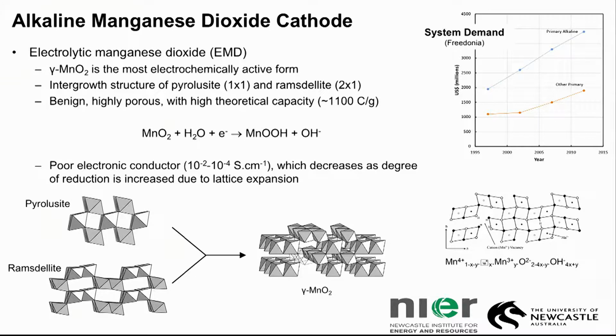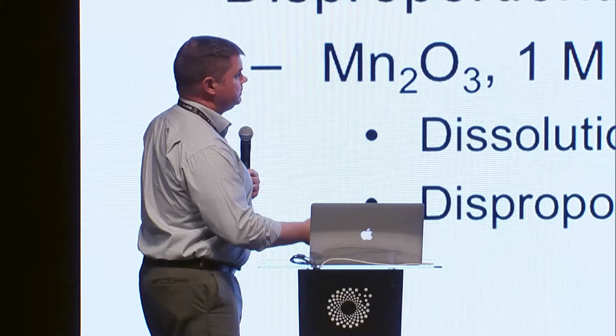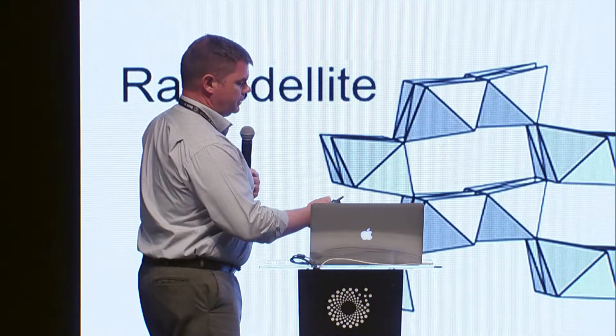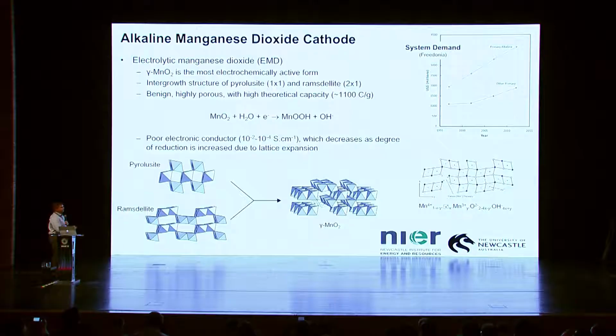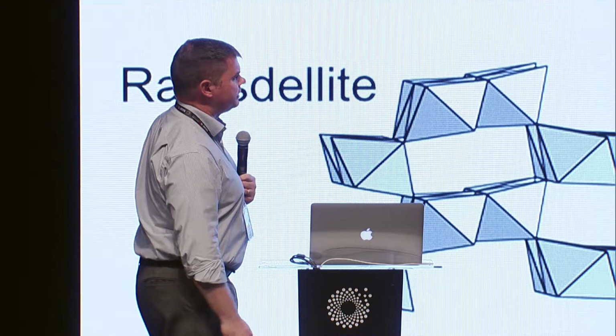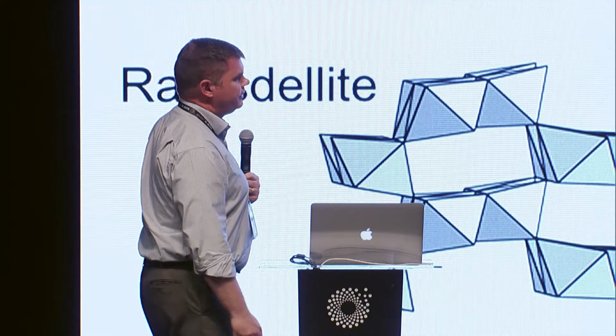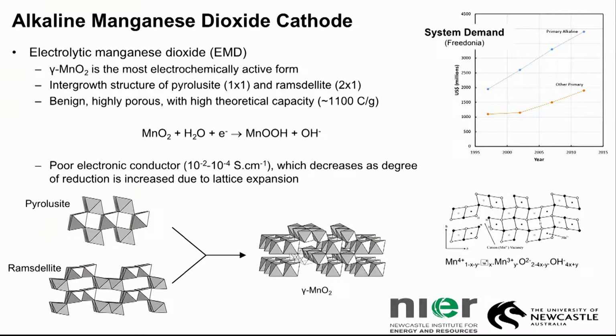But still, it's a very, very high volume system. And you can see here, keep pressing the wrong button. So you can see here in the top right-hand side basically how the dollar value of the primary alkaline system is continuing to increase with time. The basis of it all on the cathode side is the manganese dioxide, and that's made using electrolytic processes. There's some examples of the structure of the material that we're actually using. This is by far and away the most active form of manganese dioxide to use in an alkaline system.